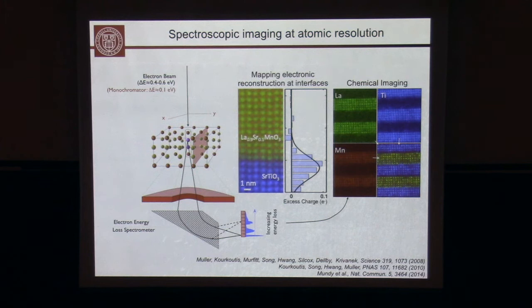And that will affect how the signal will vary across the interface. And so you need to be really careful in deciphering what is beam effect and what's actually a sample effect. So our samples, short answer, is about 10 to 15, not more than 20 nanometers. And we can measure that very accurately by looking at the diffraction pattern.